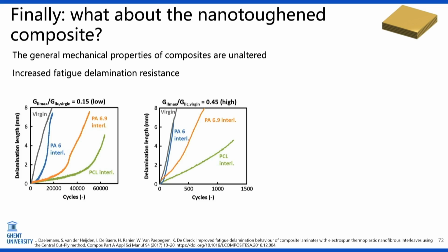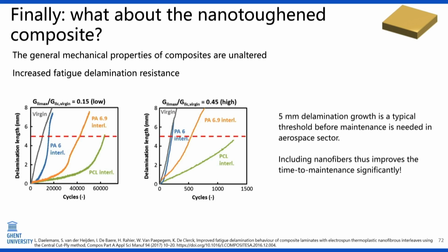After a number of cycles, we will start to get a growth of a delamination, a small crack in the beginning, and then at multiple loading cycles it grows. For instance, in airplanes, this is important. In the wings, you have different small deformations, and a crack will start to form. If we introduce nanofibers, we can delay that crack formation, and we can increase the number of cycles drastically. For the aerospace sector, a 5 millimeter delamination growth is a typical threshold before maintenance, and thus the nanofibers increase the time to maintenance significantly.